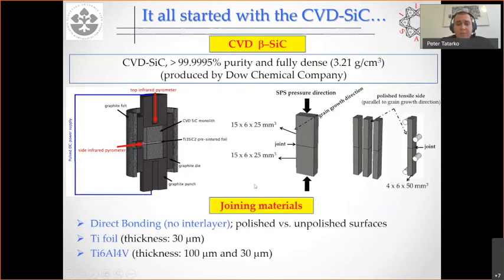As the joining materials we were using, in the first case, we call it direct bonding. So it means we didn't use any interlayer. So it seems there was nothing in here. We only compared 2 surfaces: in one case, the surface of CVD silicon carbide was polished, in the other case, it was unpolished. And then we just compared the effect of the surface roughness on the joining.